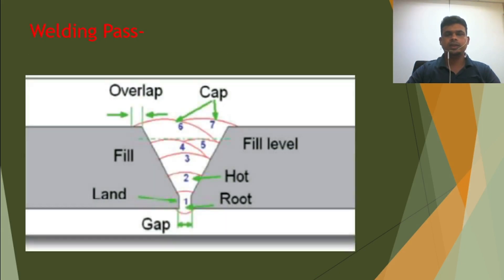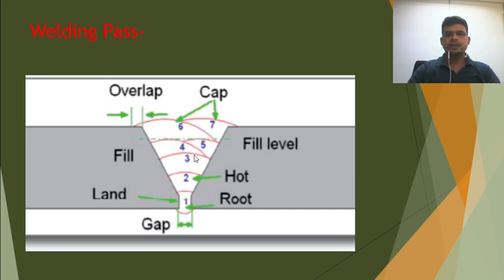Another topic is the welding pass, or welding sequence. In multi-run welding, there is a specific sequence. In a butt joint configuration with a root gap, the first run is called the root. The root is very important especially for piping — in structural work you have the chance to back-gouge and weld again, but for piping there is no chance to weld on the root side, so the root must be perfect. For piping, the root pass must always follow the GTAW process.